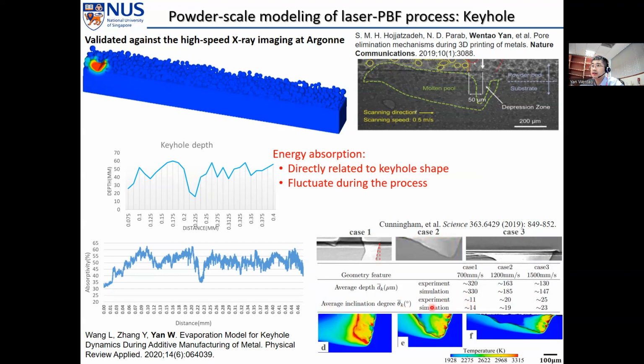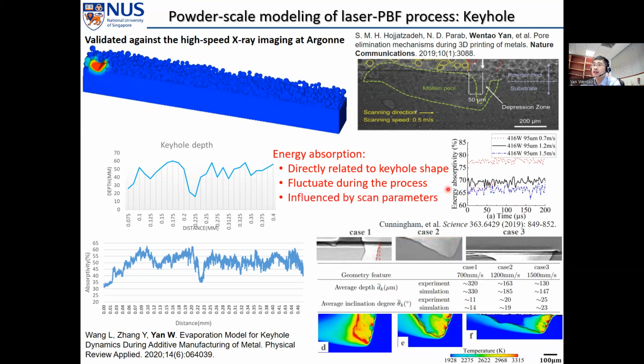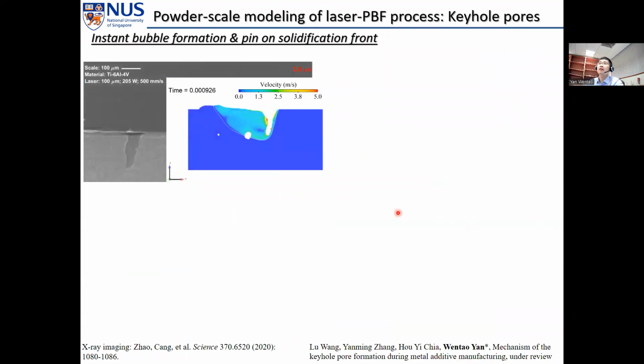Now you can see our simulation agrees well with the experiments, in both depth and inclination angle. And more importantly, we can show the energy absorptivity, which is influenced by the laser power and the scan speed. Furthermore, we can simulate the keyhole pore formation.